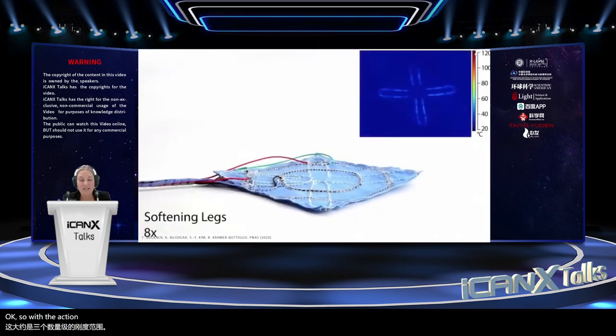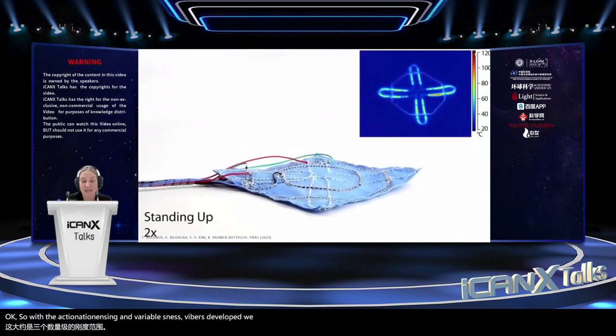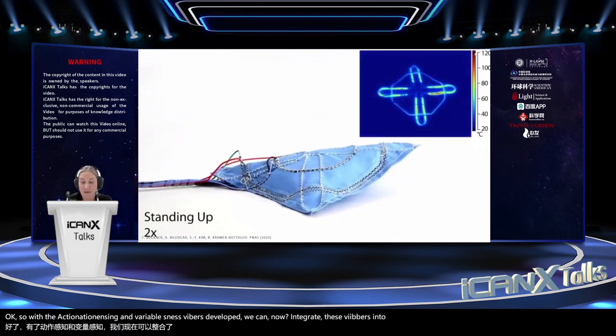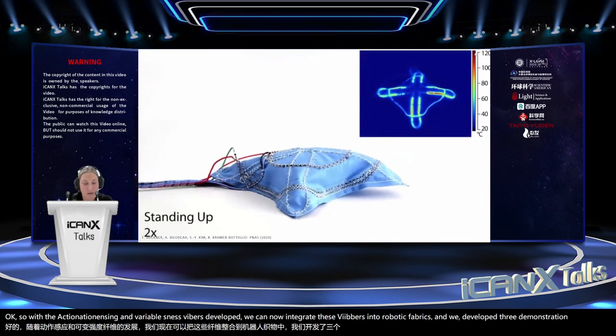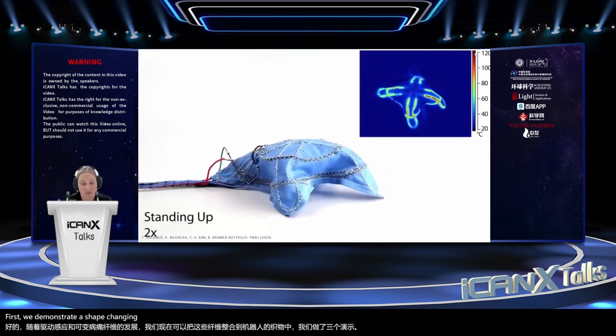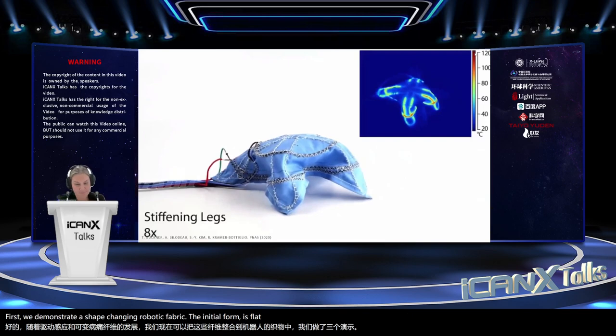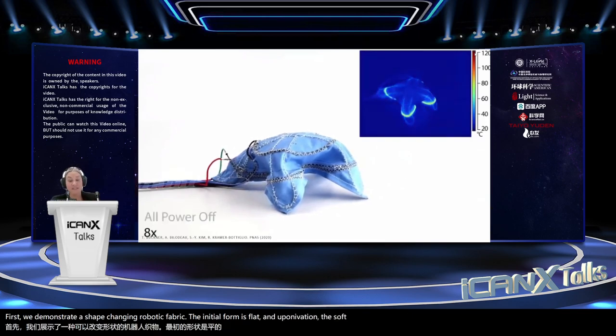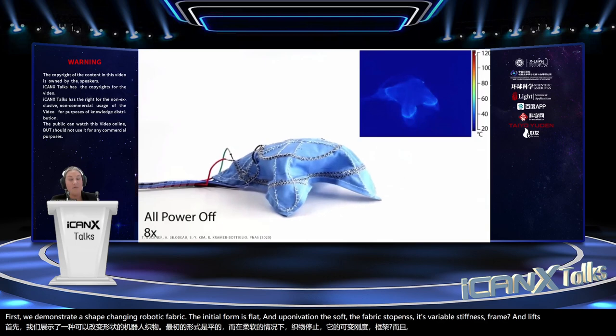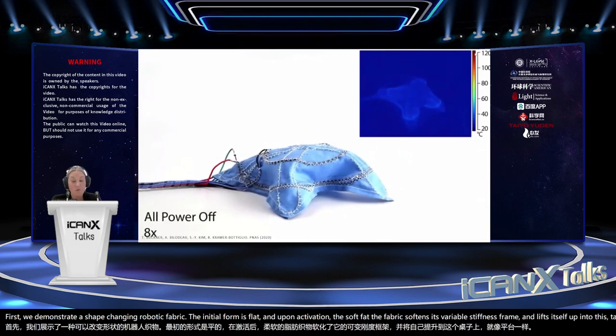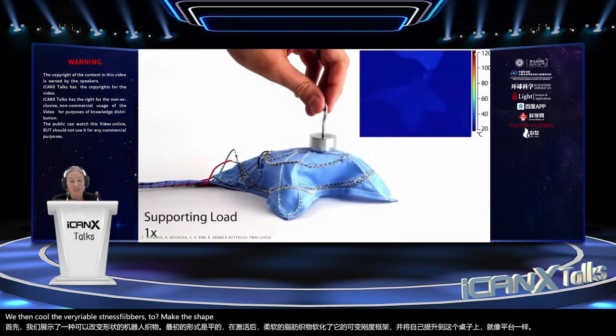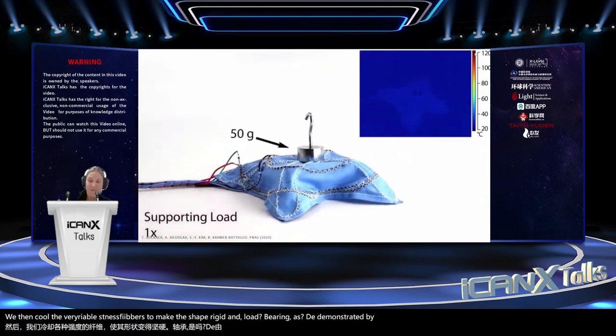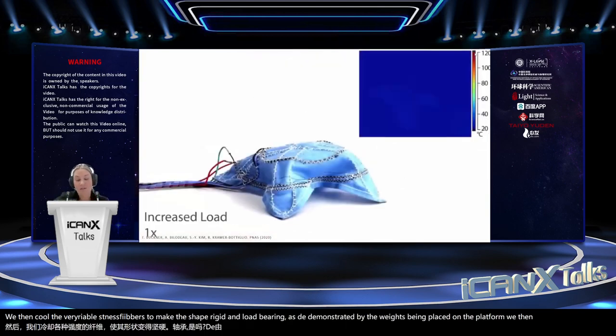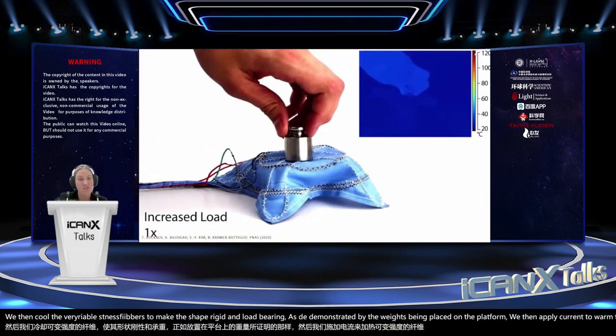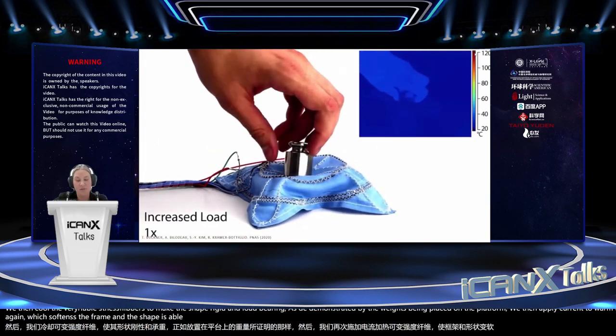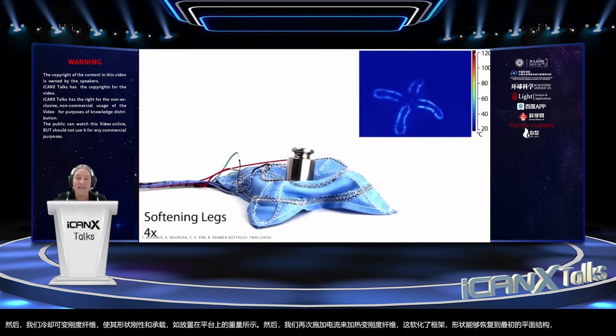Okay, so with the actuation, sensing, and variable stiffness fibers developed, we can now integrate these fibers into robotic fabrics. And we developed 3 demonstrations. First, we demonstrate a shape-changing robotic fabric. The initial form is flat, and upon activation, the fabric softens its variable stiffness frame and lifts itself up into this table-like platform. We then cool the variable stiffness fibers to make the shape rigid and load-bearing, as demonstrated by the weights being placed on the platform. We then apply current to warm the variable stiffness fibers again, which softens the frame, and the shape is able to return to its initial flat configuration using antagonistic ribbon actuators.